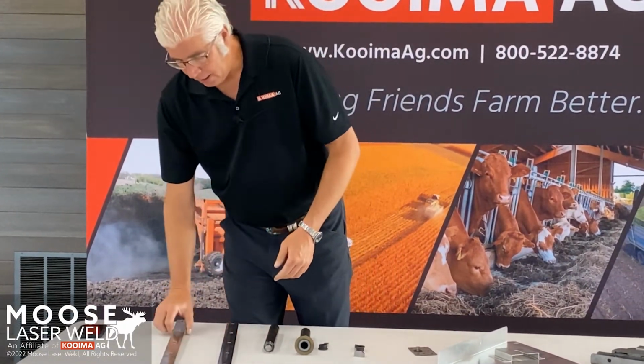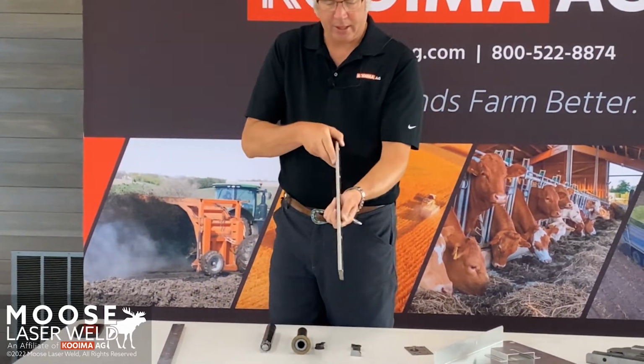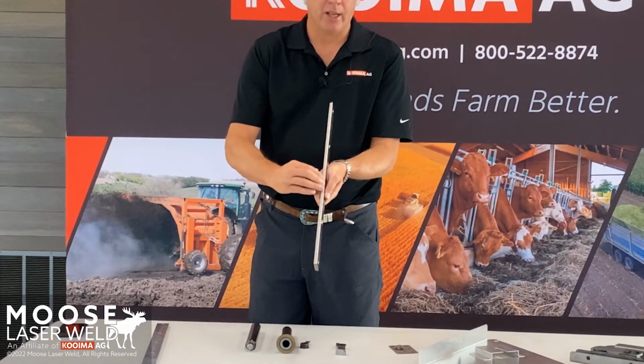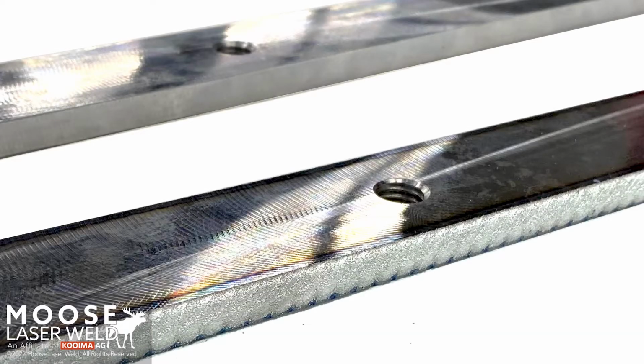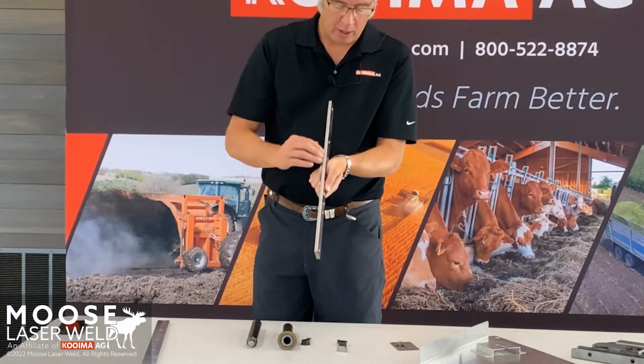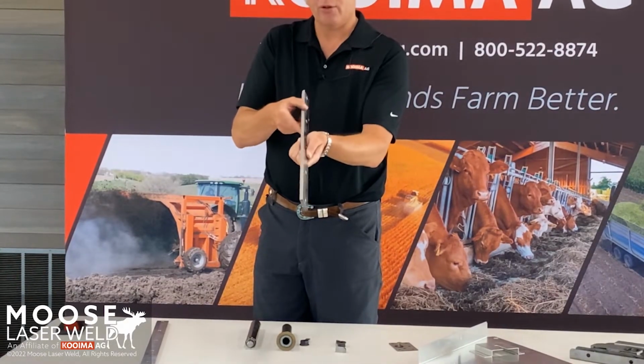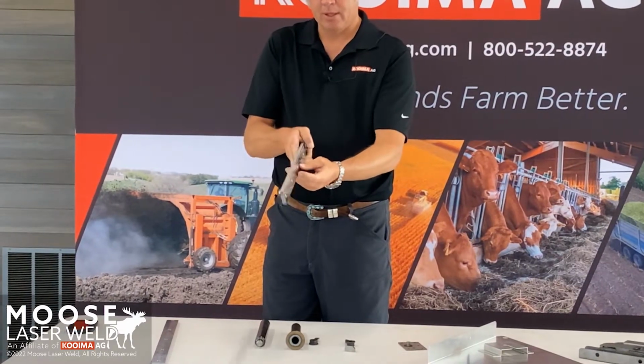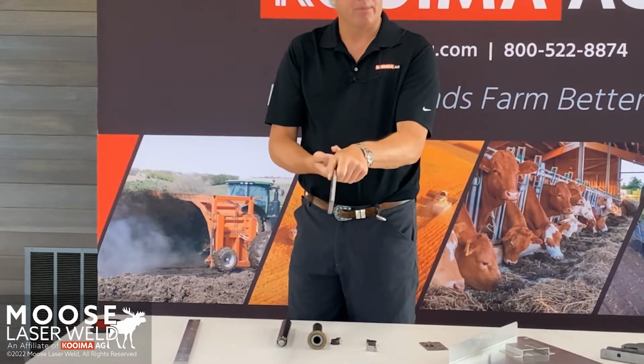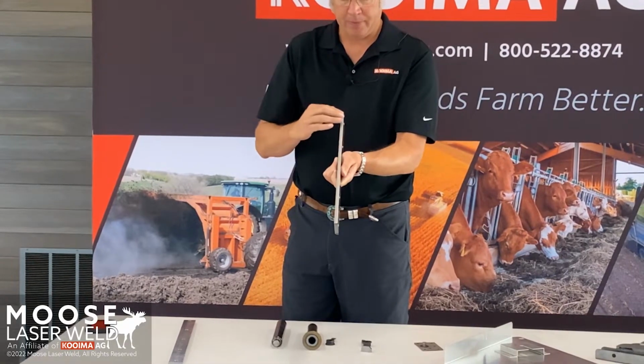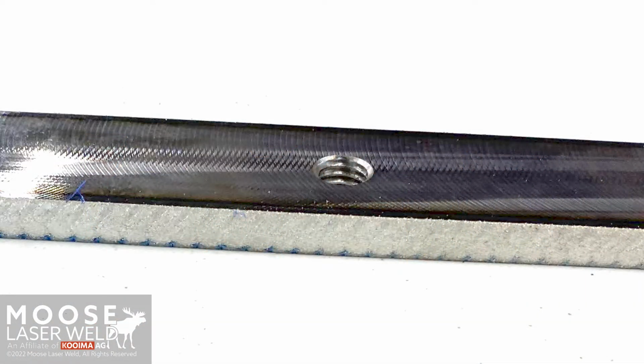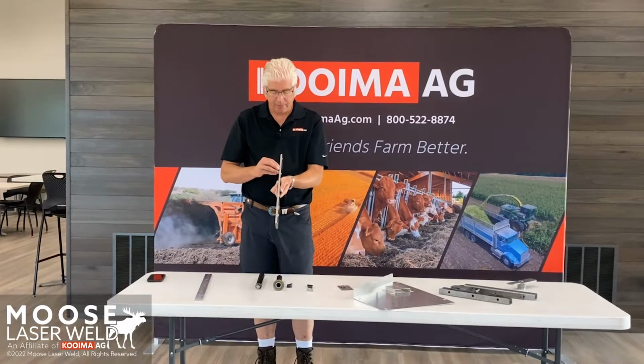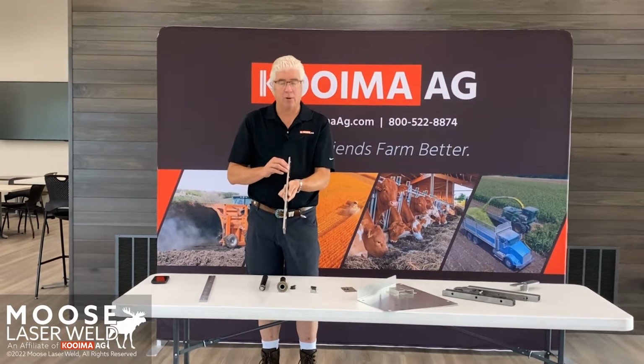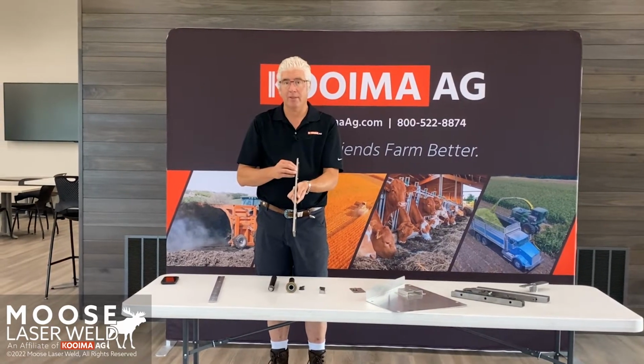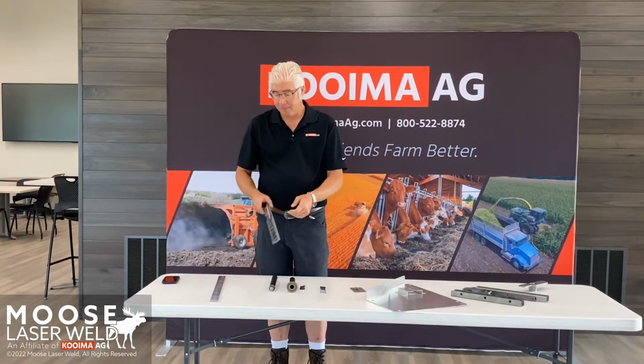And that wear bar, the guys are using the lasers to lay down a laser clad coating on the edge surface where I suspect the wear occurs to prevent wear and extend the life of these parts. And they're doing it on both sides, as you can see, top and bottom, so the part can be flipped over halfway through its useful life. And this is a laser clad tungsten carbide coating, which extends the wear life and provides a Rockwell hardness of around 65 to 67 in this application.